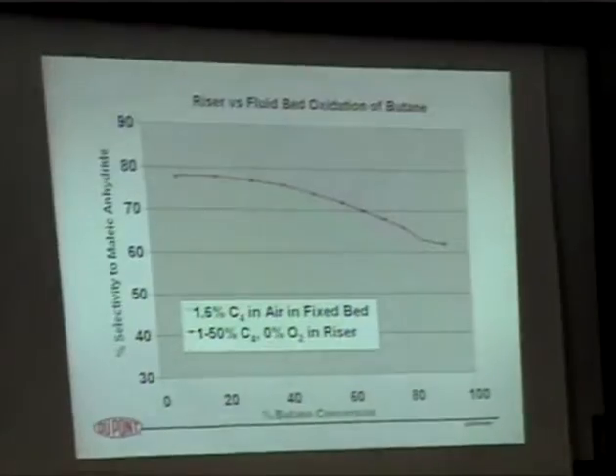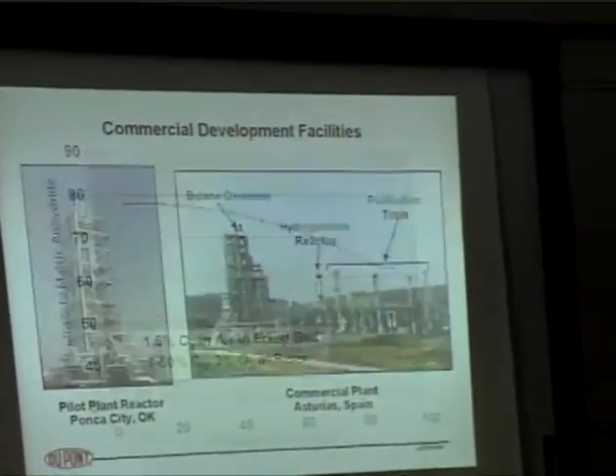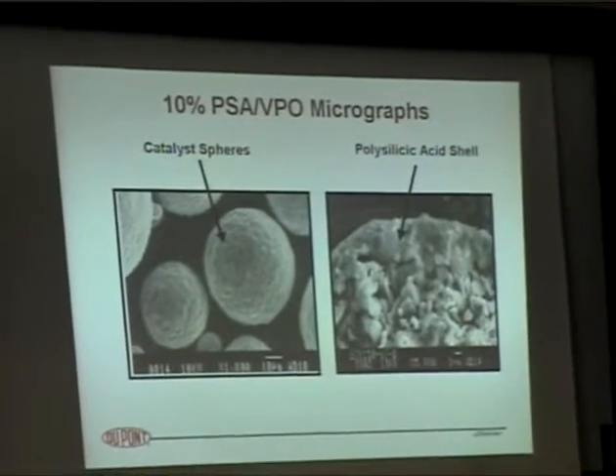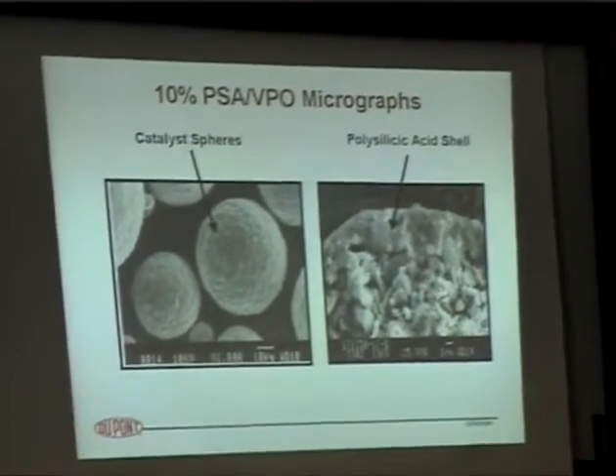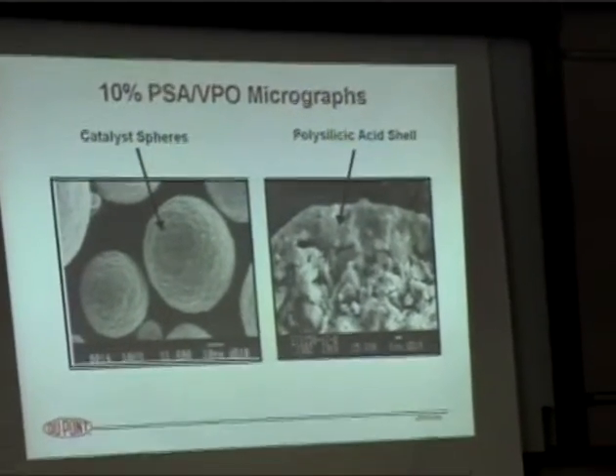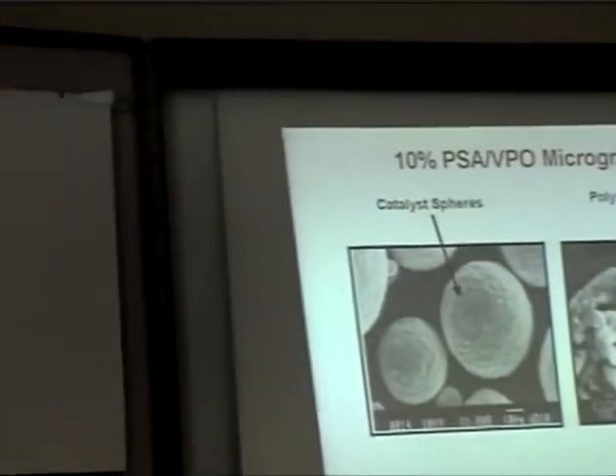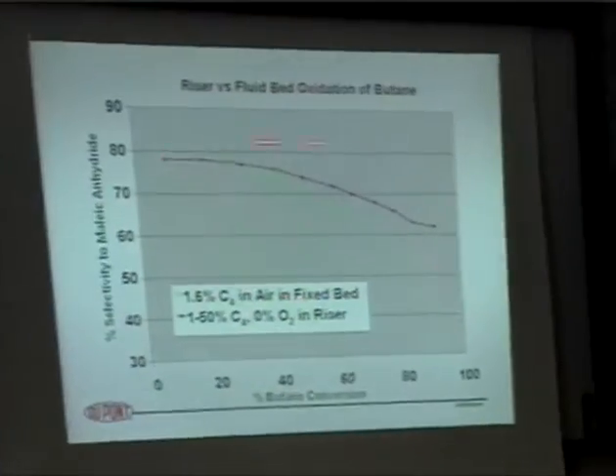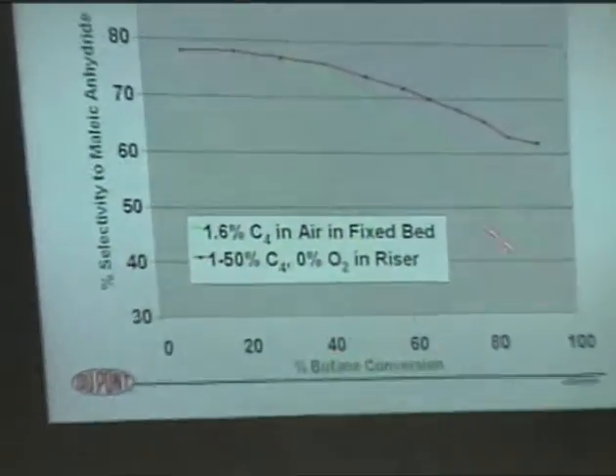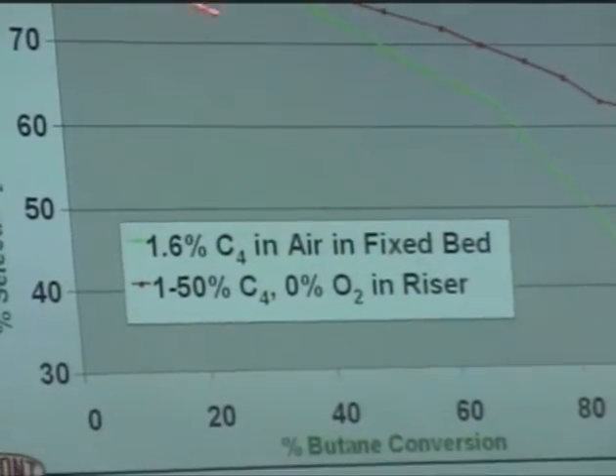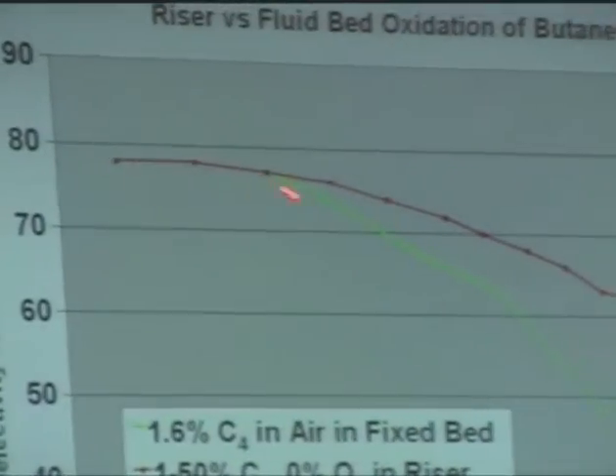This picture's been around for a long time. But you can, in fact, leach this out, and you can see a very nice hollow shell of the silica. There's only 8% there. Doesn't have an adverse effect on the performance of the catalyst at all. So the catalyst attrition has worked out extremely well, and this is a little bit of data that I can show that shows the advantage of running with no oxygen present.